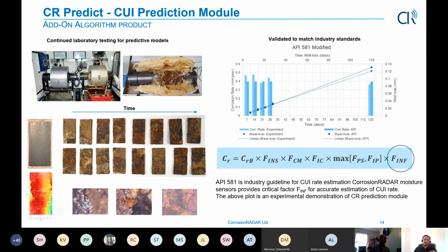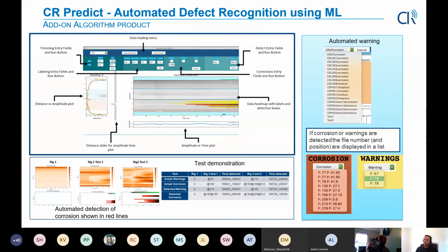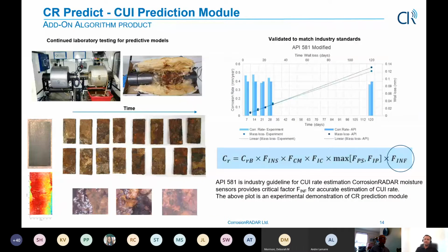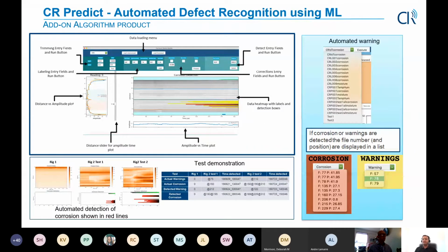Of course, there is a lot of variability. Not a lot of people agree with API 581 as well, and we tend to see a lot of variability, but that's the best set as of now. So we try to estimate the corrosion rate, and in a lot of cases, when the conditions are matching right, we see similar ballpark figures on the corrosion rates. So that's a validation scheme. If you have a specific pipe carbon steel grade for which you would like accuracy of corrosion rate, then we can benchmark that as a joint case. But we have baseline models available.